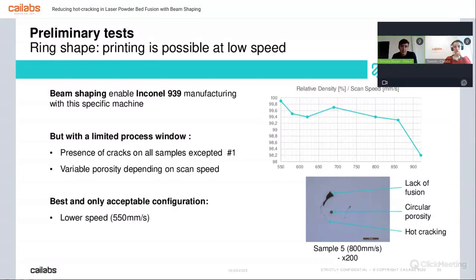And then when the melt material starts to solidify, you will need at some point the right quantity of energy at the right time to avoid the overheating of the system. So if you reduce the power, you will probably need to reduce the scan speed. And so we are not obtaining the high productivity that we want to reach with this project and in general with the laser powder bed fusion.